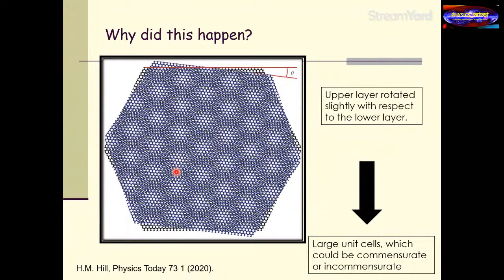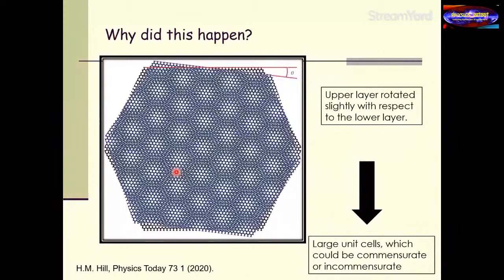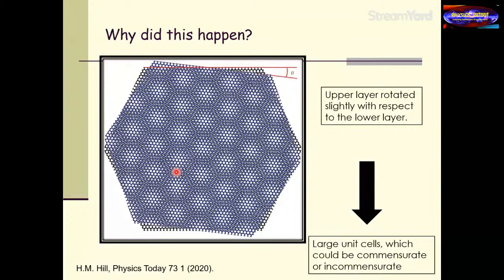Also, what you can see over here is that, depending on the angle of rotation, my unit cell size could vary. It could involve a few thousands of atoms. It could involve 10,000 atoms. It all depends on the angle of rotation. So what people thought was, if your unit cell size is very, very large, that means your reciprocal space, which goes as 1 over your lattice, is very small. Suppose I'm talking about A as my lattice parameter in real space, then my reciprocal space would have dimensions of 1 over A. So if A is very, very large, my reciprocal space is going to be very, very small. So they thought that one should view these as giant